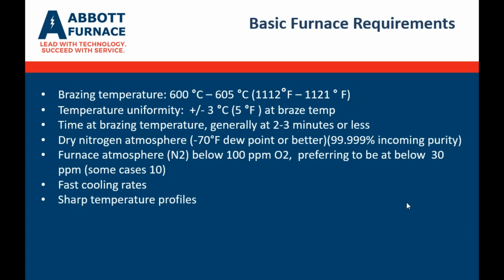As far as furnace atmosphere inside of the furnace for the process, the Nocolok handbook states that it must be below 100 parts per million of oxygen in the part. That will get you a successful braze. But in some applications, you're preferring to be at below 30 parts per million.